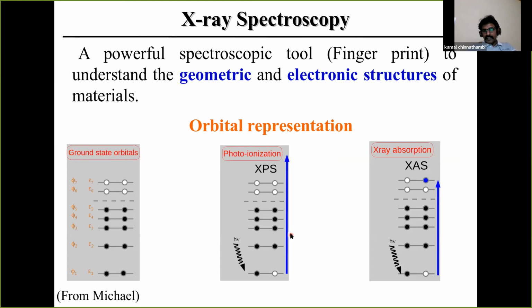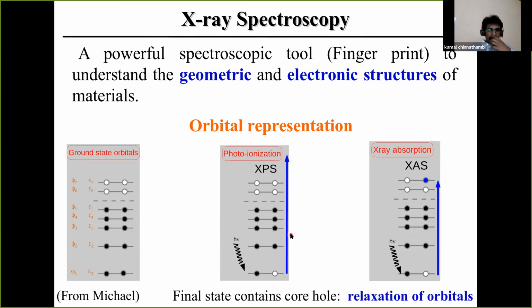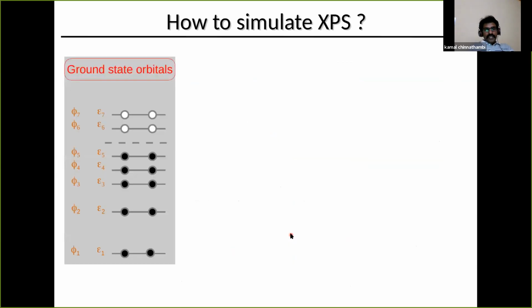Once you have a core hole present in the system, all the other occupied orbitals also need to be relaxed if you want to give a correct description of the final state. So that is very important. The orbitals we represent in the ground state and in the excited state can be different because of the orbital relaxation. That we need to take into account. That is very important if you want to give a correct description of the electronic structure of the excited state. So how do we do it?